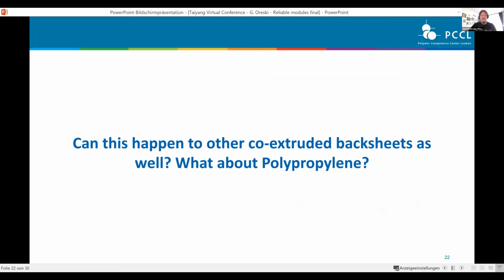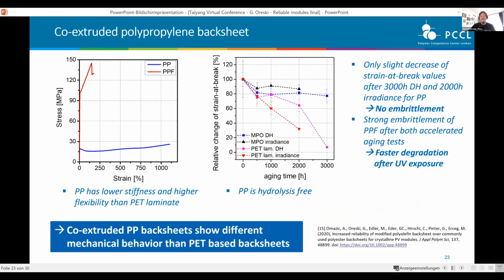So, what about polypropylene? Can this happen to polypropylene as well? Let's take a look at the properties of polypropylene backsheets. So, as you see from the strain curves, it's quite different to a PET-based backsheet. So, we have lower stiffness and a higher flexibility. When we expose the film to some damp heat and irradiance, you see polypropylene is quite stable, whereas for the PET, we see very quick embrittlement.